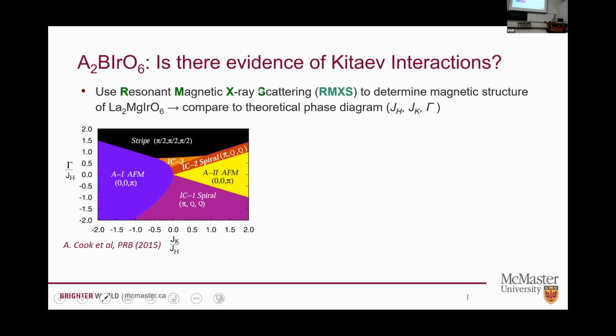Okay, so these calculations tell you for different interactions what kind of ordered structures you expect to see. We go out and measure the structure. That should give us an idea what kind of interactions might be at play. So we've got this theoretical phase diagram for these double perovskites. It includes a Heisenberg term, a Kitaev term, and this gamma term, the off-diagonal exchange.